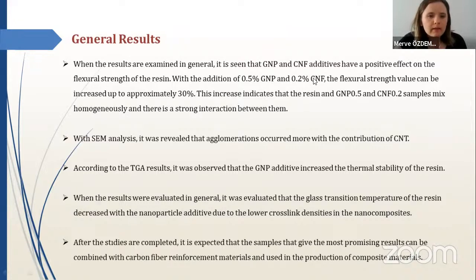With some SEM analysis, it was revealed that agglomeration occurred more with the contribution of CNT. According to the TGA results, it was observed that the GNP additive increased the thermal stability of the resin. When the results were evaluated in general, it was evaluated that the glass transition temperature Tg of the resin decreased with the nanoparticle additive due to lower cross-link densities in the nanocomposite. After the studies are completed, it is expected that the samples that give the most promising results can be combined with carbon fiber reinforced materials and used in the production of composite materials.